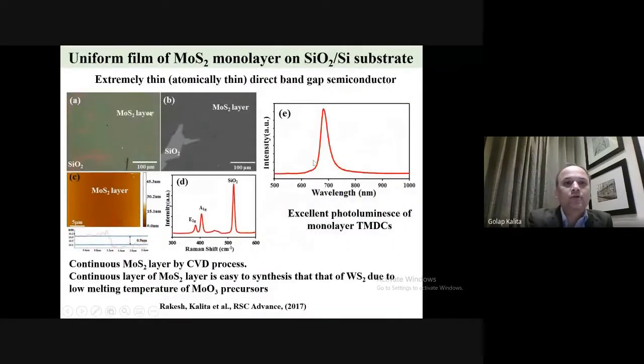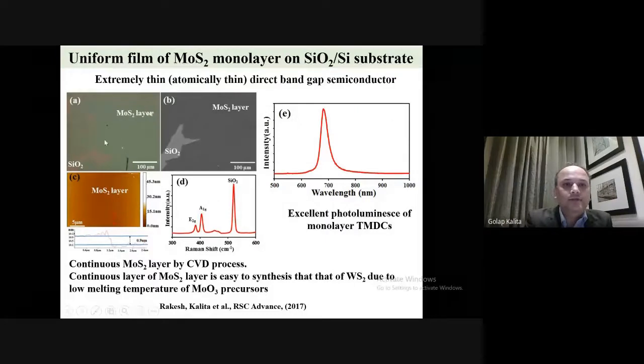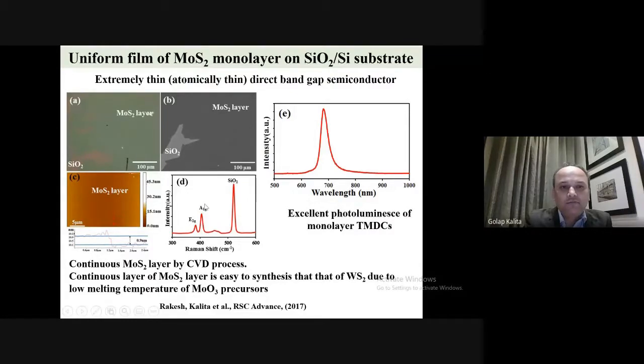We can grow a very nice continuous film. So this is MoS2 layers on silicon oxide, and the same in an SEM image. Because it's a single layer with a direct band gap, you can get very good PL, photoluminescence, from a single layer. But if you have bulk MoS2, you will not get any kind of PL. So by growing a monolayer, you can evaluate the quality of the single-layer MoS2 by its photoluminescence properties.